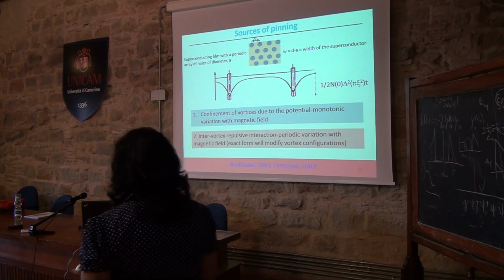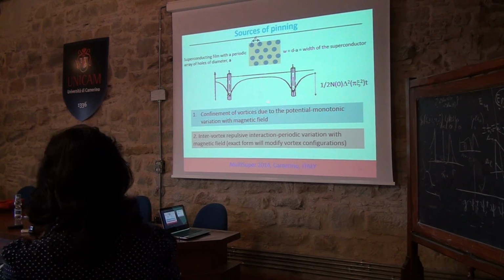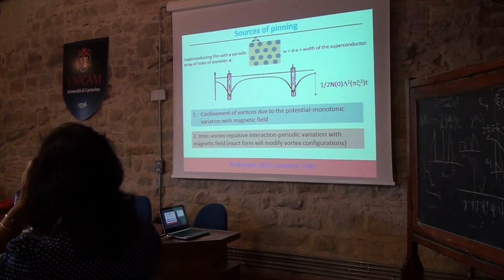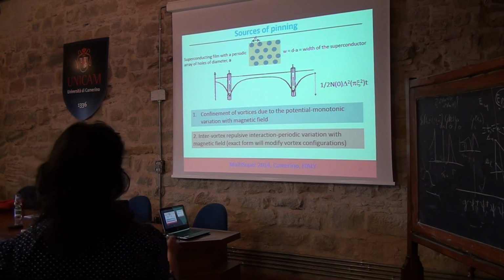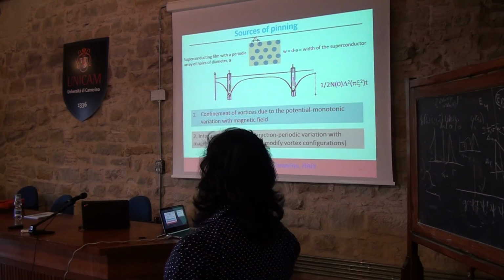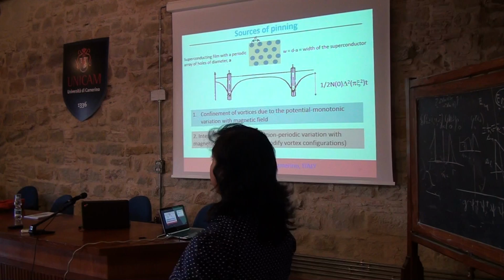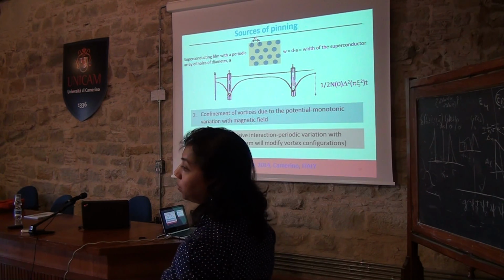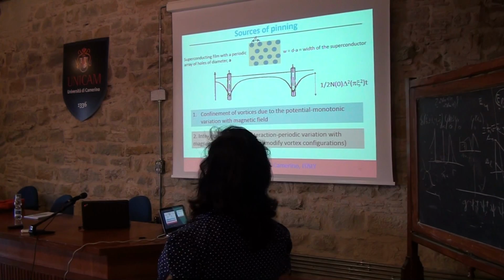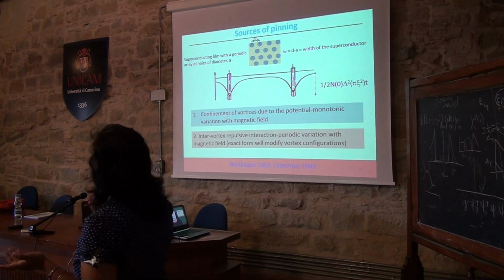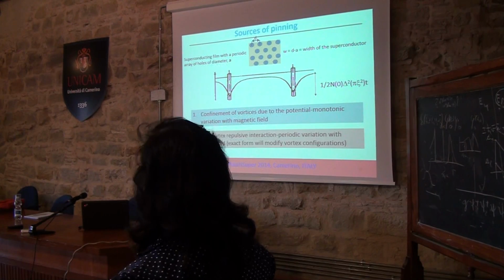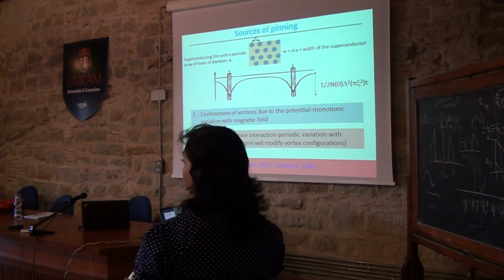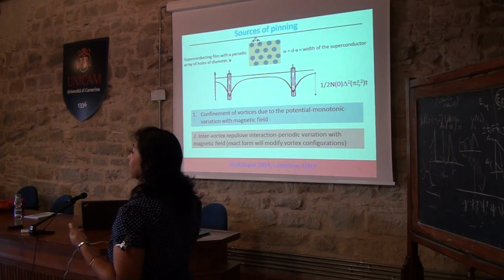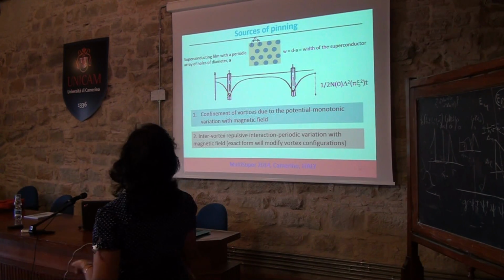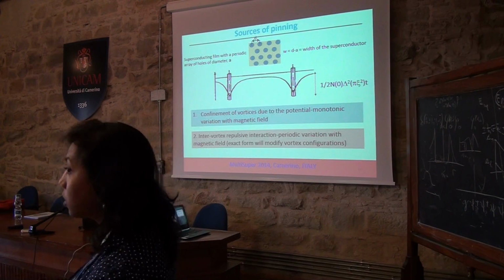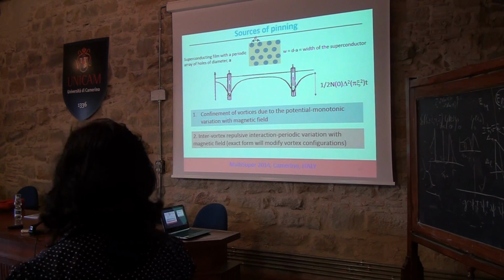In this kind of model, there are two sources of pinning. First, of course, these holes act as a potential well. The height of the potential well is proportional to the condensation energy. When you increase the magnetic field, the height of the potential well will only decrease. So the potential will become shallower, and you will just get a monotonic variation with magnetic field. The pinning will just vary monotonically with the magnetic field. It will not give rise to any oscillatory behavior or the matching effects which we see.